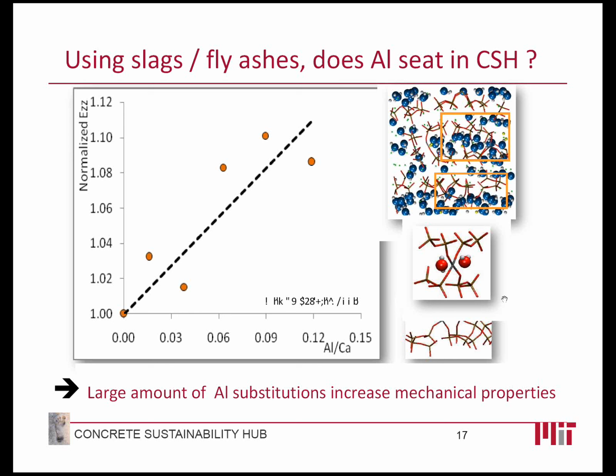I mean, the idea is that if we are to improve the mechanical properties of cement, we need to substitute the calcium side, and to do so, we need to first substitute the silicon side. So it means that we go first for the silicon and then the calcium. This is why we need to consider a lot of substitutions of aluminum in the structure. So the idea is to put a lot of aluminum rather than a few.